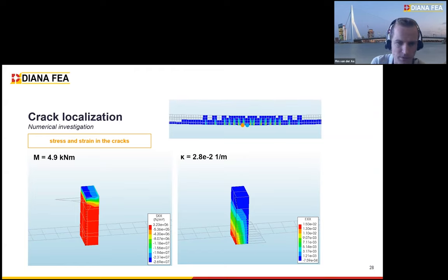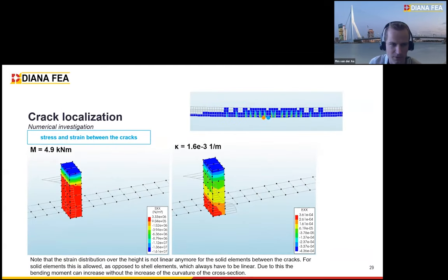So the bending moment at this moment is 4.9 kilonewton-meter, and the curvature is about 2.8 times ten to the power minus 2. If we then go to the next slide, we can see what is going on with the stress strain distribution between cracks. You can see that the bending moment is exactly the same value, but the curvature is a lot smaller. That can be obtained because the strain distribution over the height is not linear anymore.